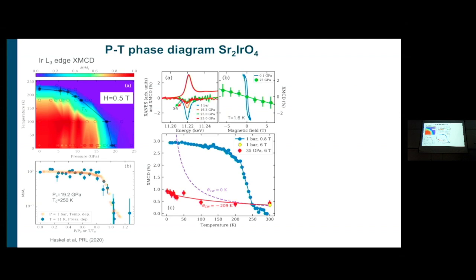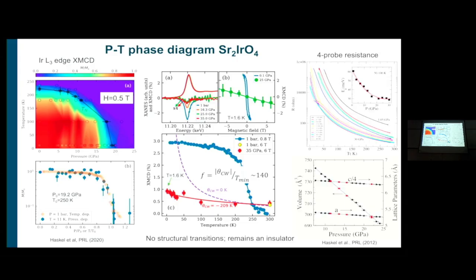There is no magnetic order, but there is strong correlations between the spins. This magenta curve is what you would expect from the susceptibility if it was just a Curie paramagnet with no correlations between spins. This is what we measure, and even at 1.6 Kelvin there is no ordering, so very strong frustration and a linear dependence of the magnetization at 35 GPa, and it also remains an insulator. So this is a resistivity measure at high pressure. It remains an insulator, and there is no lattice anomalies.